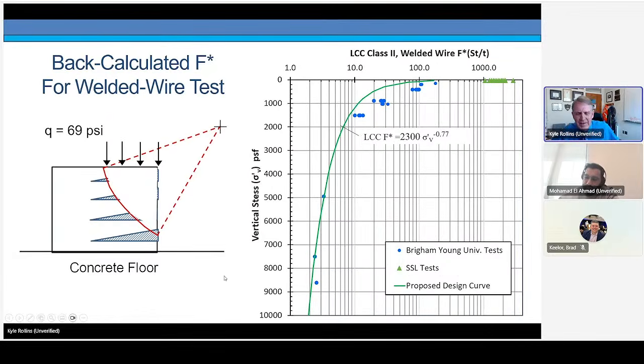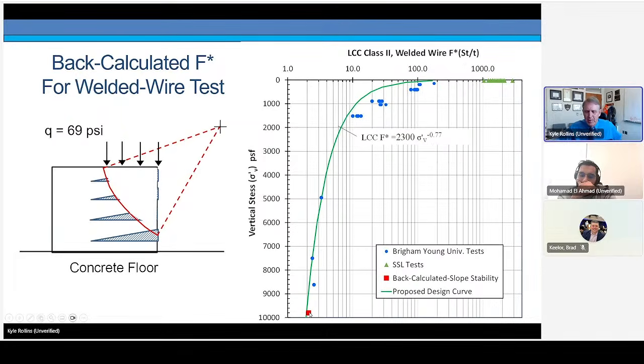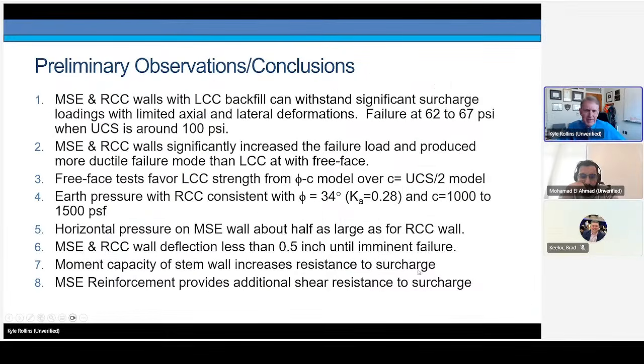And then this case involves welded wire reinforcement. So I'll put the curves up for the welded wire. And this point comes in very nicely with the results from the pullout tests that we've done previously. So that was very satisfying after finding out that we couldn't get it to fail if we were using values like we were seeing up here at lower confining pressures. So let's summarize here